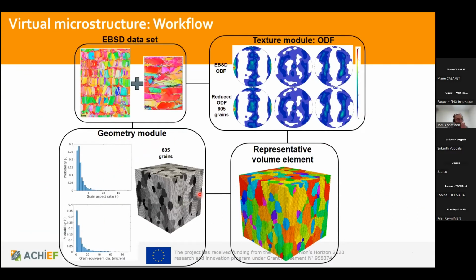So after that, when we synthesize the material and produce it with different methods, these two different 3D printing methods, laser sintering and direct energy deposition, are used here. When we have those and do the characterization for those, we can produce these synthetic models to analyze the behavior of the material in this environment. So basically we scan those materials with EBSD, take different statistics out from the EBSD analysis, and build this kind of synthetic model based on those.